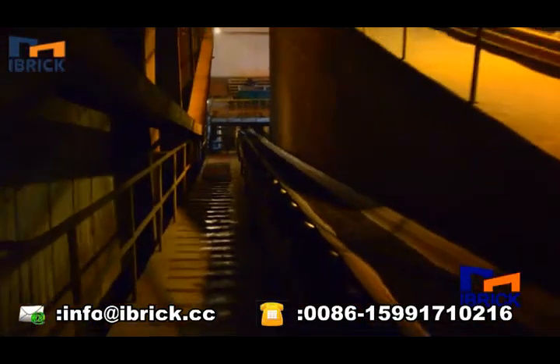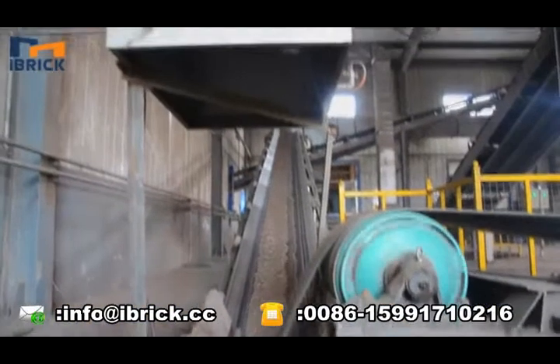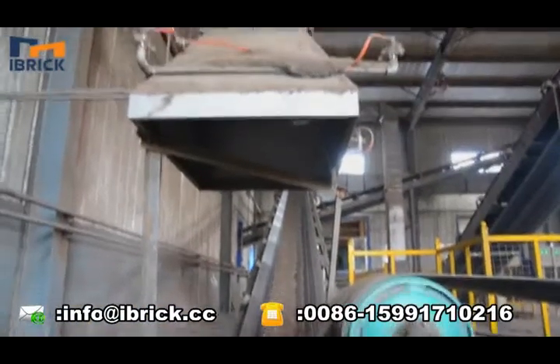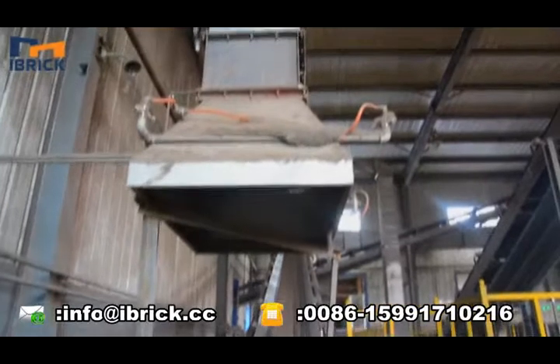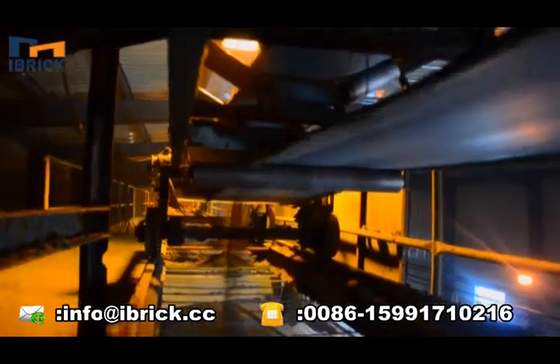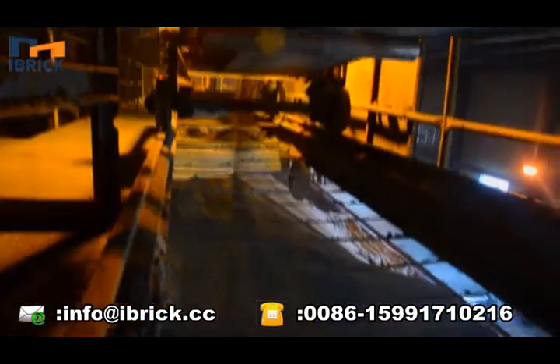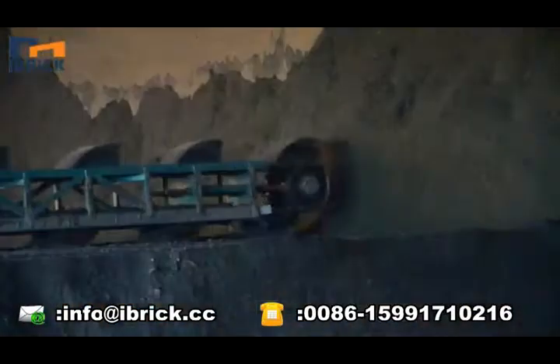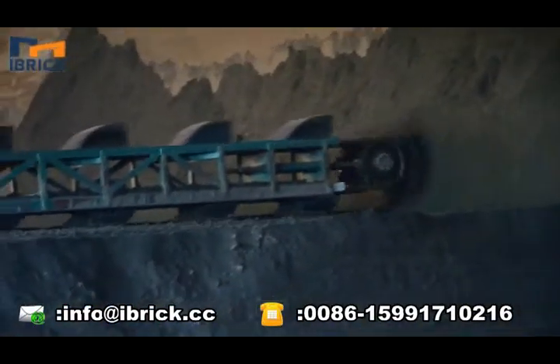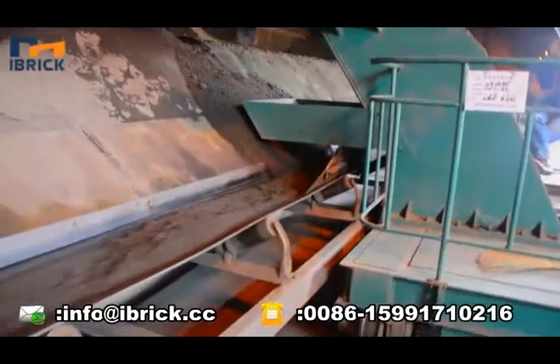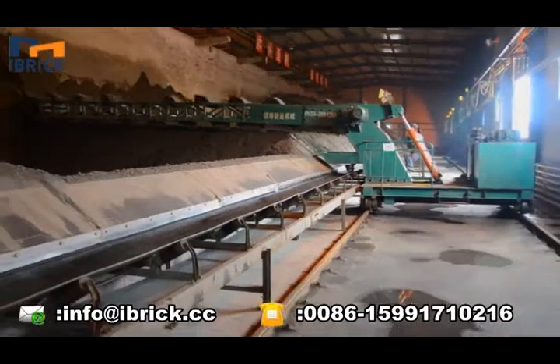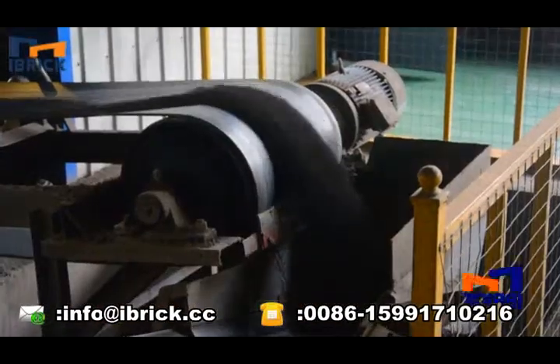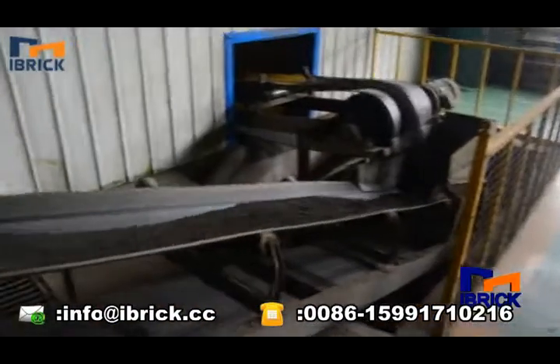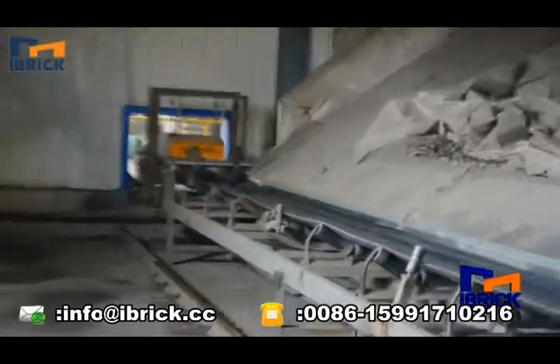The storage capacity of the aging room is 21,000 cubic meters. Aging time is about 72 hours. The moisture content of aged material is 12% to 13%, reduced by 1%. The material will be unloaded onto the belt conveyor on the side of the aging room by a multi-bucket excavator, then sent to the box feeder before starting the molding process.